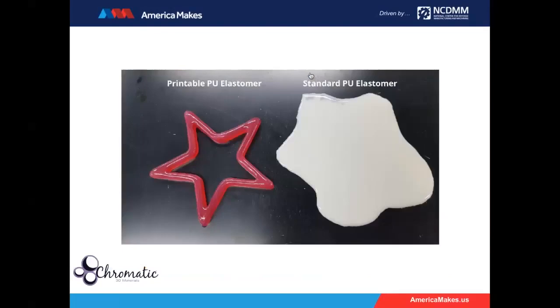So what is special about what we do? Well, if you were to take a standard polyurethane elastomer and place it in these same pieces of equipment, you'll get just a blob. But if we print with our materials, we really customize the viscosity and the cure rate and the chemistry so that we get a very solid part as it's printing. So we can get well-formed definition that you expect from 3D printing.